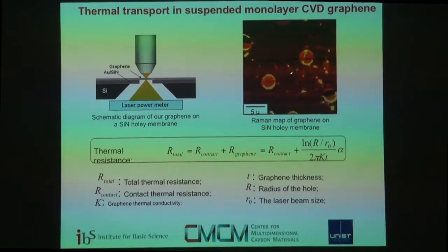And when you have that geometry, then you have, for the total thermal resistance, this expression. This can be determined by measurement. All of these parameters are geometric parameters, with the exception of the thickness that everyone agrees to use 3.4 angstroms for. And so with that thickness, then you can extract the thermal conductivity from this sort of measurement.